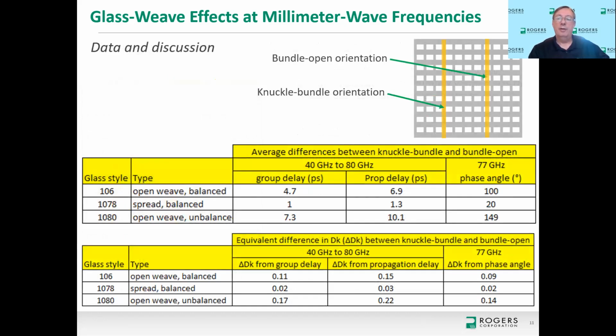So here's a summary of one of these studies, and what the table information is showing is differences between the circuits that were oriented to the knuckle bundle orientation and circuits oriented to the bundle open orientation when using the same laminate. In this case, the study had four different laminates in it. The table information that I'm showing just shows three of these laminates, and I'll get to the fourth one later. Three of these laminates used a glass that was open weave, spread weave, and open weave. The glass styles shown on the left are 106, 1078, and 1080. The description of the glass is the next column over under type.